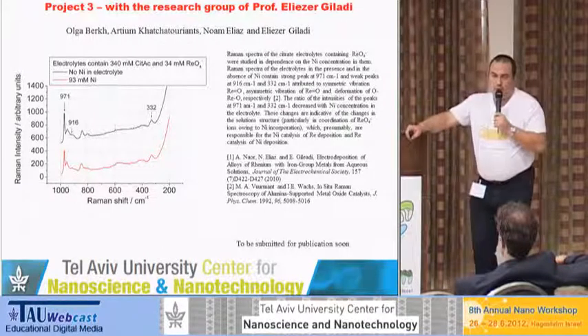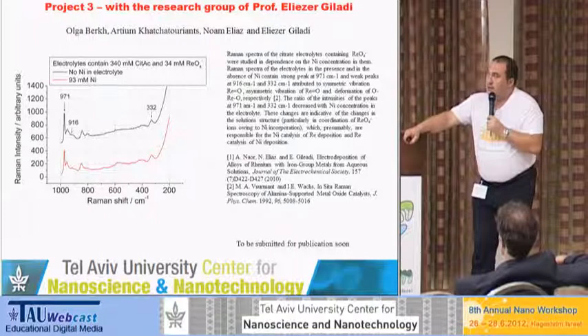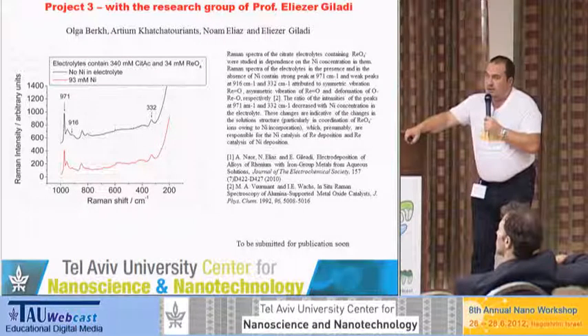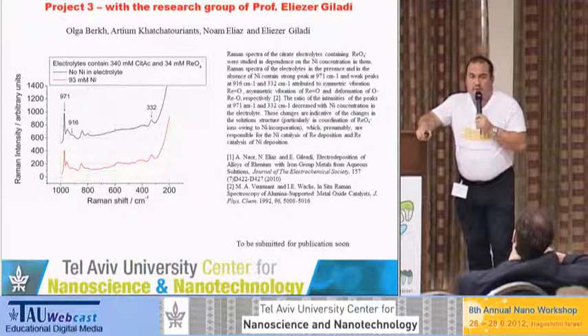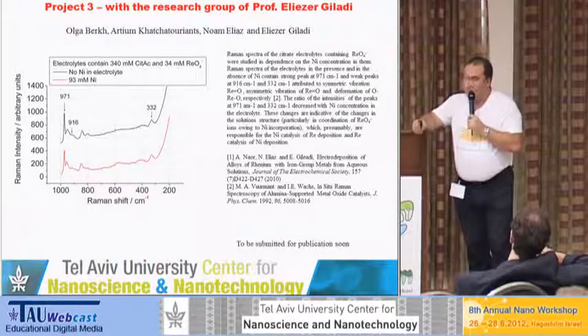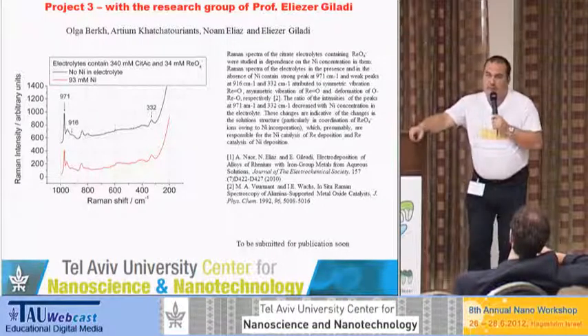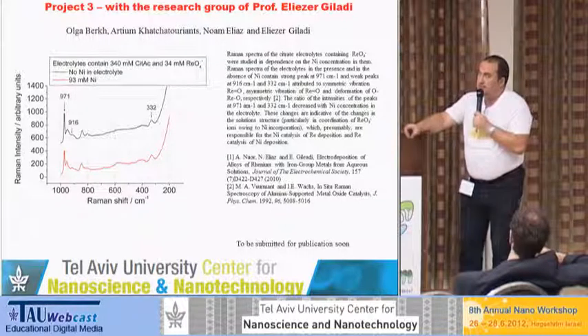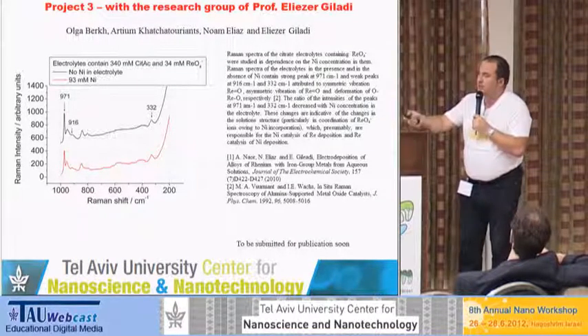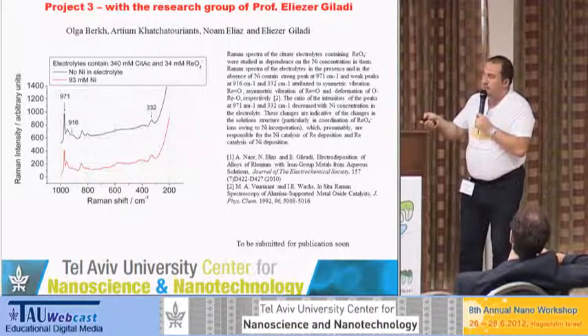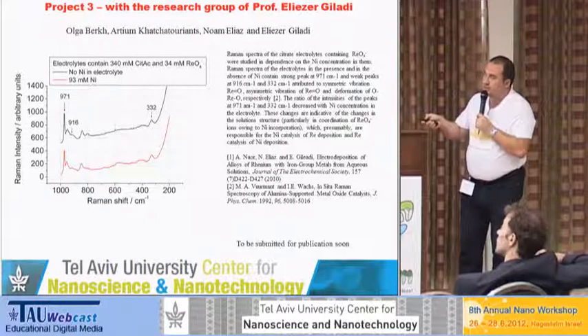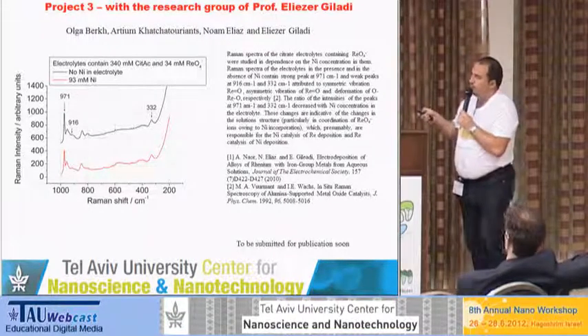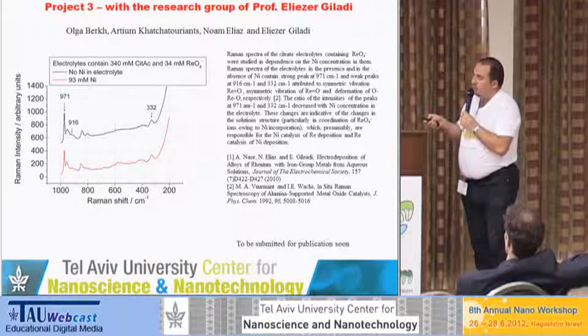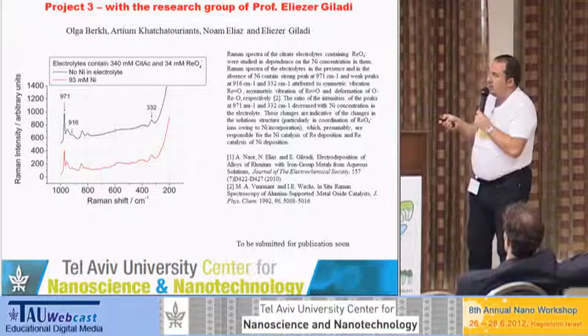And here there are not many techniques that can actually do that, and we tried Raman for these purposes as well. First of all, as you can see here, Raman can be used not only for solid samples, but also for liquids and even for gases. And we tried many solutions, and finally we found out that there are actually 3 peaks on these characteristic shifts, which originate from different bonds of rhenium with oxygen atoms in the ReO4 ions.